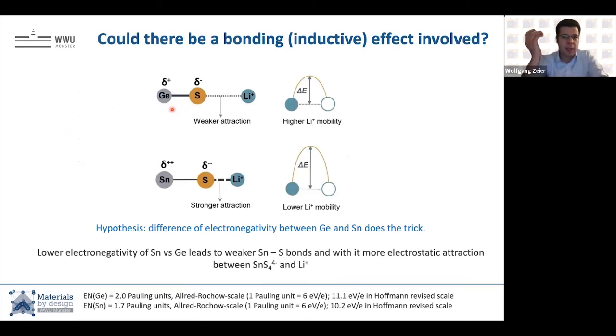And one idea was that there could be an inductive effect involved, with the idea that if we change from germanium to tin as the central element in these polyhedra, the bonding interaction would change. The electronegativities are shown down here. Germanium is more electronegative, more electron pulling, and should pull charge density away from the sulfur. Whereas tin, less electronegative, should have longer bonds anyway because it's larger, and because it's less electron pulling, we should have more electron density sitting here on the sulfur. More electron density should then mean, in terms of Coulombic attraction, a much stronger Coulombic attraction if we have tin in the system than if we have germanium.